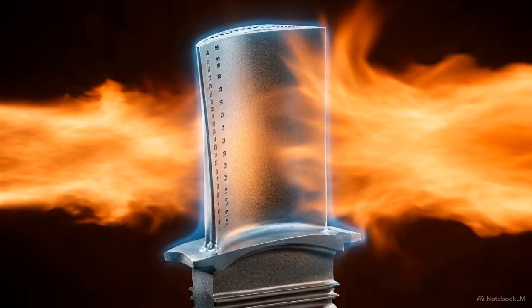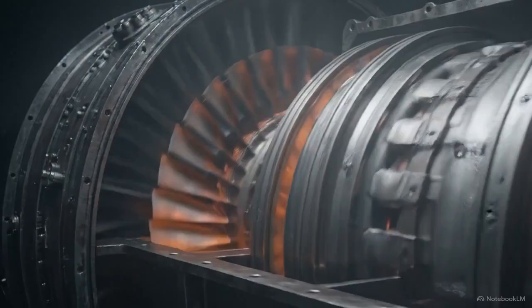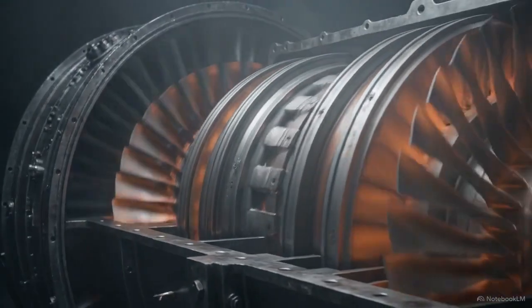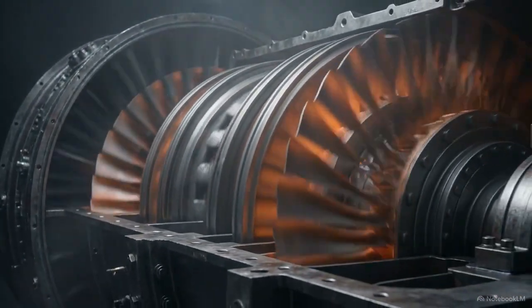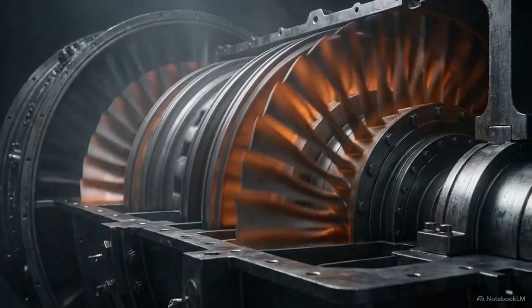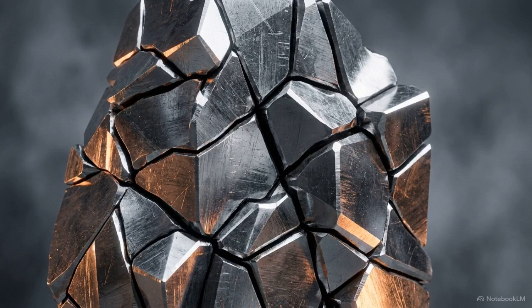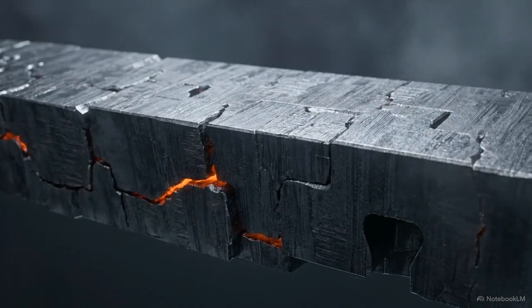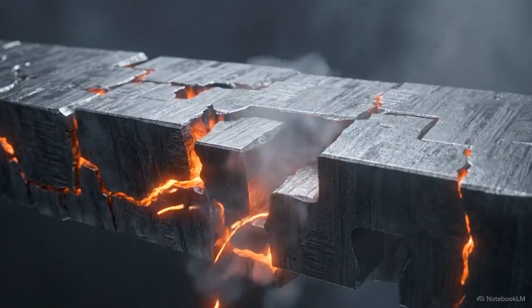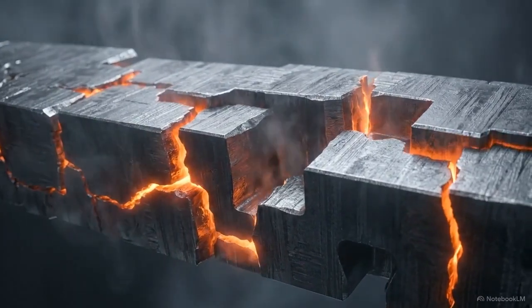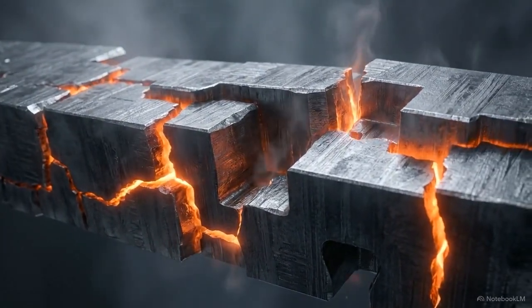In this regime, the turbine operates as an active system of thermal survival, designed to exist in conditions that would liquefy standard hardware. The blades in the first stage face a combined threat: extreme heat and massive centrifugal stress from spinning at thousands of revolutions per minute. Standard cast metals are comprised of microscopic grains. Under severe stress, the boundaries between those grains become natural weak points. This leads to creep, the slow, catastrophic stretching and cracking of metal under sustained load. In a turbine, creep starts specifically at these microscopic grain boundaries.